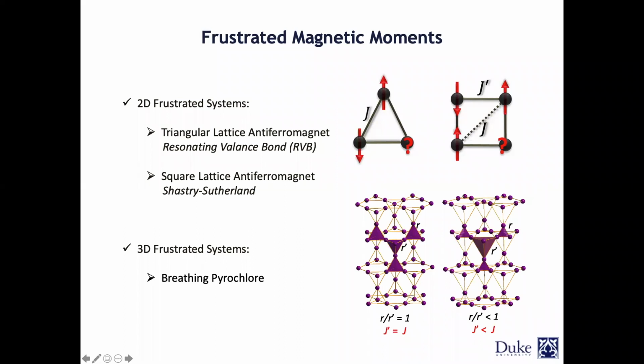So let's look at this. This figure that I'm showing on the left is showing just a pyrochlore structure. So you have this corner-touching tetrahedrons, and then again you're having this triangle geometry, which is going to introduce some frustration. R and R prime are going to be, for example, the size of these tetrahedrons, and J prime is going to be equal to J. So the nearest neighbors and the next nearest neighbors are going to have the same sort of interaction.